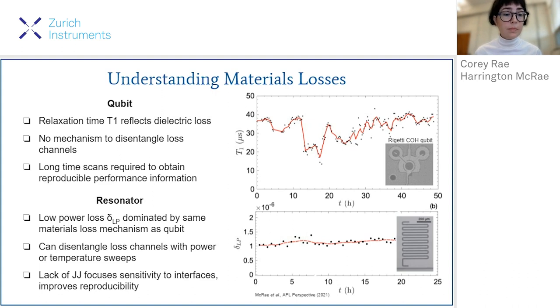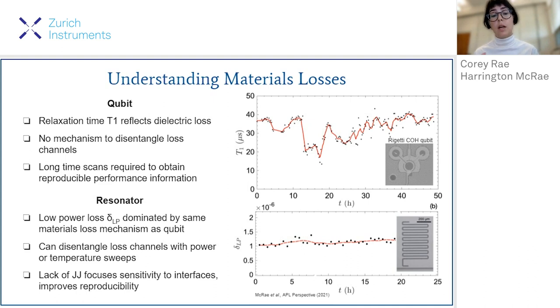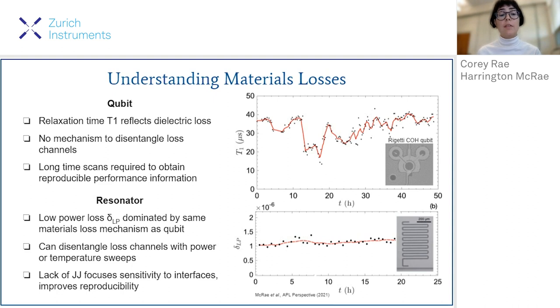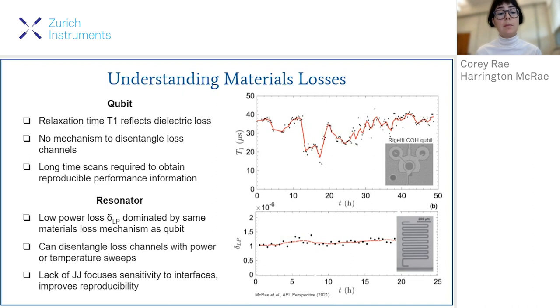We always want to bring things back to qubit performance ultimately. There are several types of resonators used in materials experiments for superconducting qubits, each giving different information. Lumped element resonators let us implement thin-film dielectric materials in a parallel-plate capacitor, sensitive to losses in that material and its interfaces. We can also measure a superconductor patterned on a bulk dielectric into a CPW — coplanar waveguide — which is the most common form of materials loss investigation being performed now for state-of-the-art qubit improvements.